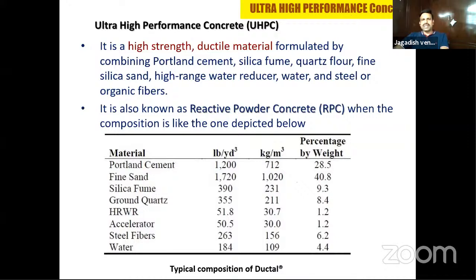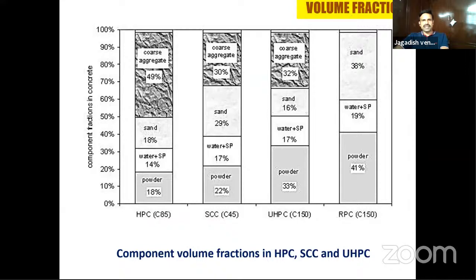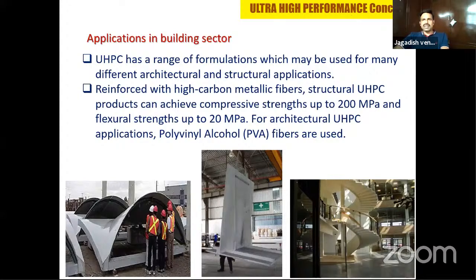And ultra high performance concrete and reactive powder concrete are special applications, with a lot of combinations of materials, so composite materials you use. Silica fume, quartz flour, fine silica sand, water reducer, various fibers. This is the difference between the high performance SCC and ultra high performance. You can see here in case of reactive powder concrete, there is no coarse aggregate present. In ultra high performance concrete, you can see around only 32%. Even SCC also you can see. This ultra high performance concrete or reactive powder concrete is used for specialized applications, particularly architectural curves or whatever shapes. If you want, you can use this kind of concrete. And it can produce up to 200 MPa of compressive strength and 20 MPa of flexural strength.